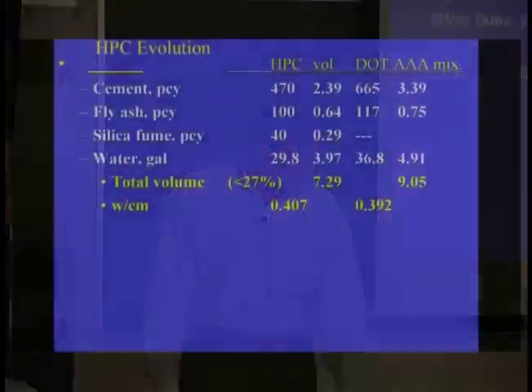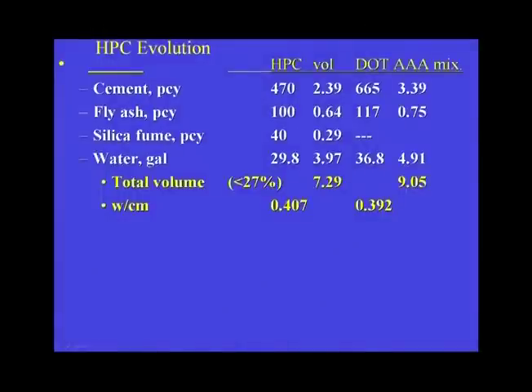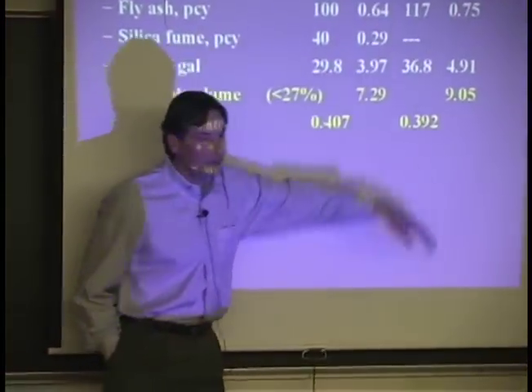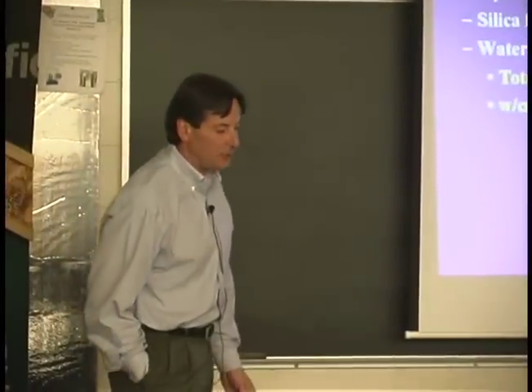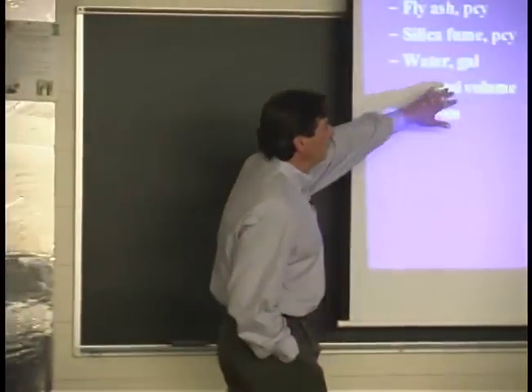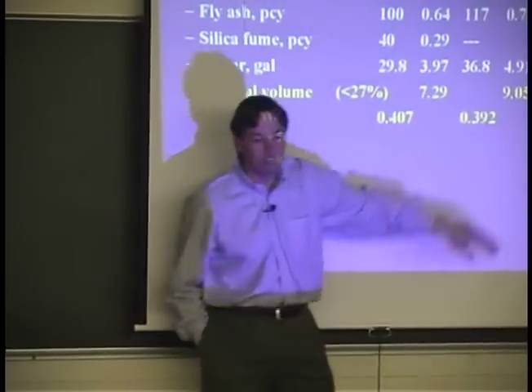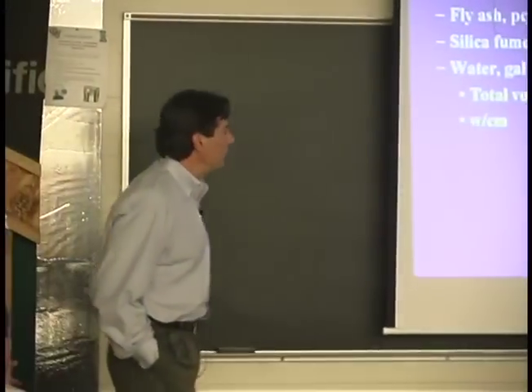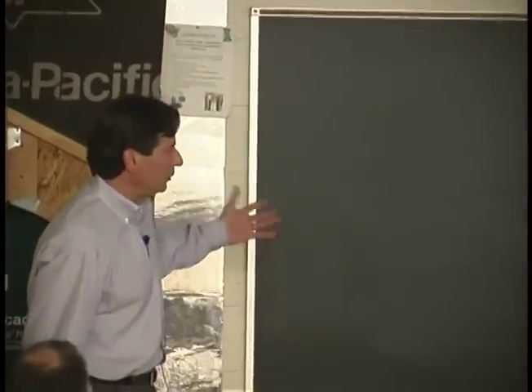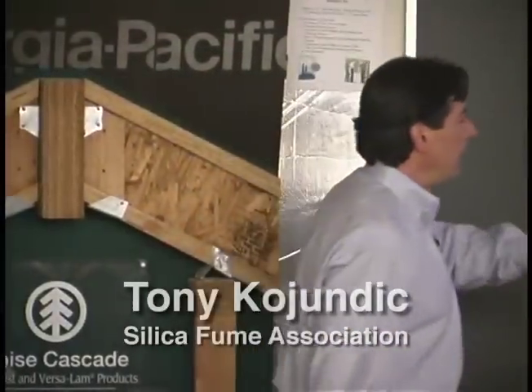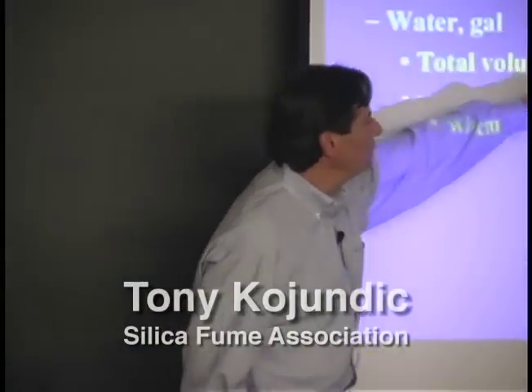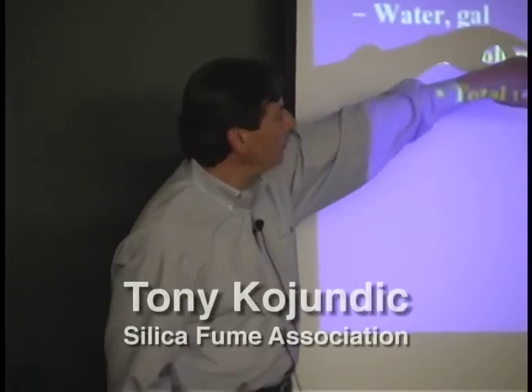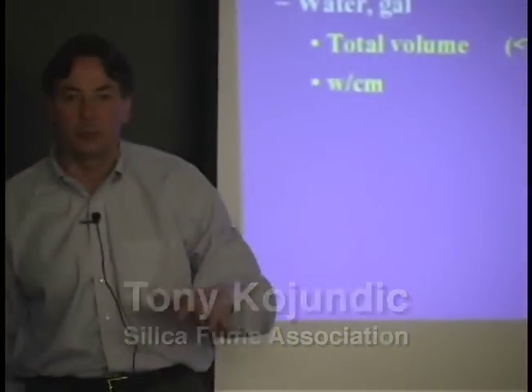This happens to be the Illinois Tollway mix on the Chicago Skyway Bridge that was done two years ago, in '03. This was their starting mix design with a high cement factor, 665, some fly ash in there, no silica fume. The water, the gallons of water, this is the absolute volume that the mortar occupies. And you see what they ended up doing when they switched over to a high performance concrete. They took out almost 200 pounds of cement. Fly ash is approximately the same. They used silica fume here at 40 pounds. And if you think about it, this 40 pounds, we said that 5-to-1 cement replacement.